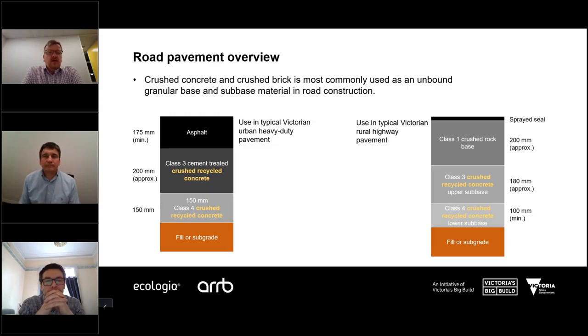It sits on top of a cement-treated sub-base. Now that sub-base can be either virgin aggregate or it can be purely crushed recycled concrete. It's approximately 200 millimetres thick, and cement is added to form a bound material, so we expect it to be bound. So the re-cementing of the material isn't a problem there, it's desired, if anything. So that material can be 100% crushed recycled concrete. That sits on top of an unbound sub-base, which is also a working platform that the rest of the pavement can be constructed on top of. That can be either a Class 4 virgin aggregate or a Class 4 crushed recycled concrete. The Department of Transport specifications pretty much treat the materials as equivalent to each other.